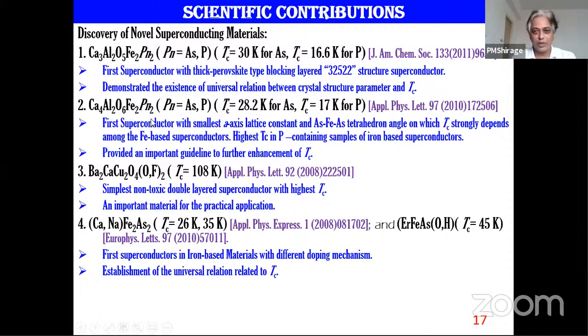Then the 42622 superconductor. This is also published in very reputed journals, the Journal of the American Chemical Society and Applied Physics Letters. Then another important superconductor which I discovered is barium 2, calcium, copper 2, oxygen 4, oxygen fluoride. It does not have any bismuth, thallium or mercury, but still it superconducts at 108 Kelvin. So this is the simplest non-toxic double layer superconductor with a TC of more than 108 K. Then I also discovered calcium sodium iron 2 arsenide 2 superconductor, and erbium iron arsenic hydroxide. Both of these superconductors have a TC around 30 Kelvin.